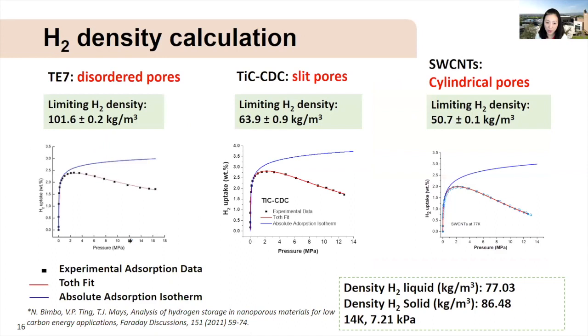And I used mathematical modeling to fit the experimental data, and then we can calculate the hydrogen density from it. And we can see that in all three shapes, hydrogen can be densified to a very high density. And TE7, the disordered pores, shows the highest hydrogen density, even higher than solid hydrogen density.